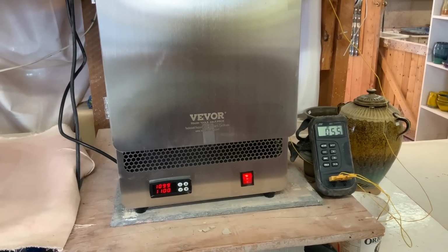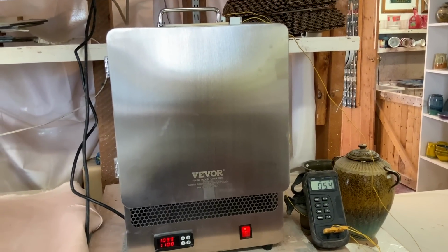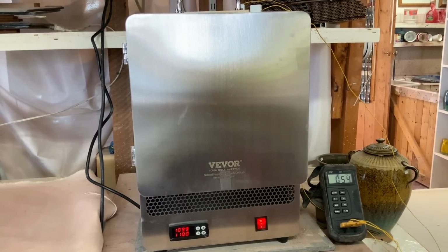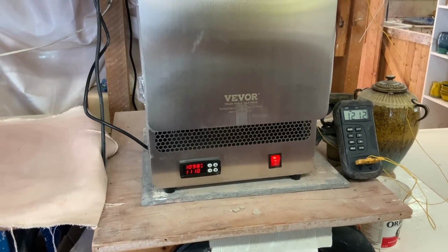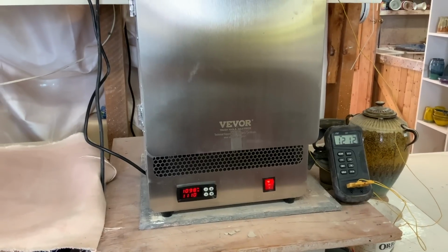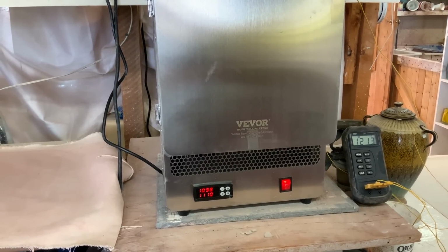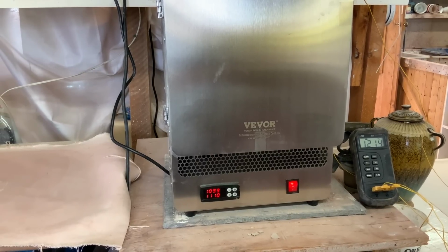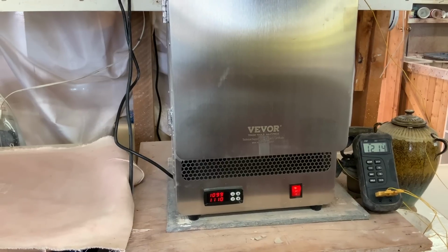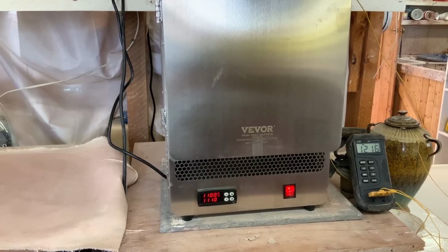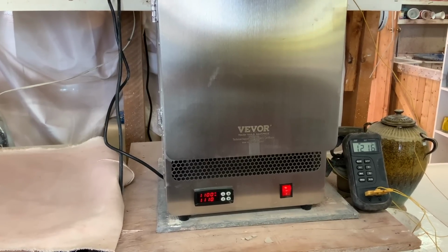Just to give you an idea, the outside of the kiln with my other thermocouple laying on the top there is 54 degrees centigrade, so that is a hot day in Australia. I just raised the temperature of the kiln itself to 1110 because we seemed to be stuck at 1098. It hadn't increased to the 1100 I'd set it at, so I'm going to give it 1110, and now we should see some increase because the kiln controller is recognizing it's got to get up to a higher temperature. Yeah, it just went to 1099, and my thermometer is reading 1215, so I don't want that to go above 1225. So that should mean that the kiln should get to 1110, and it'll be at 1225 on my pyrometer.